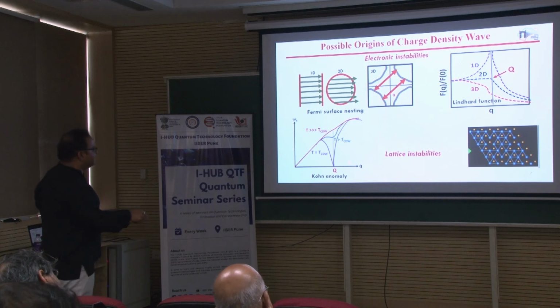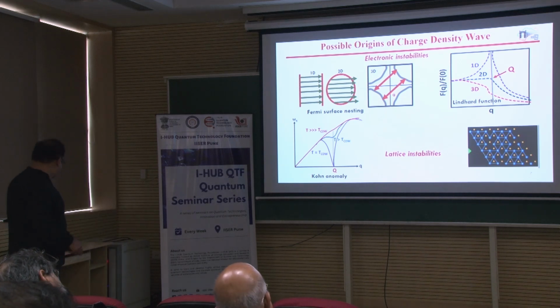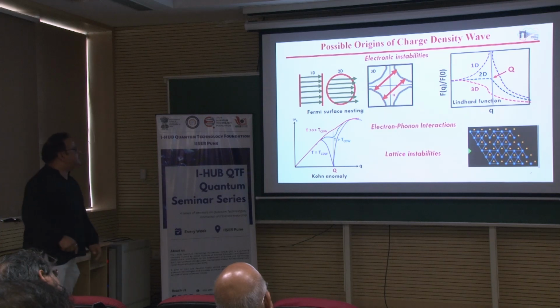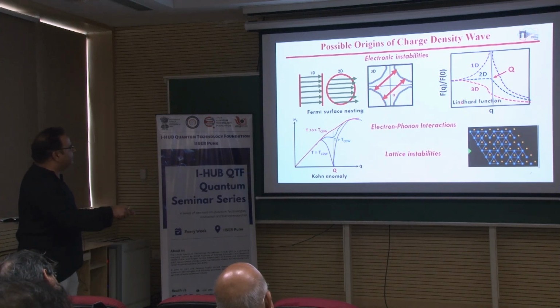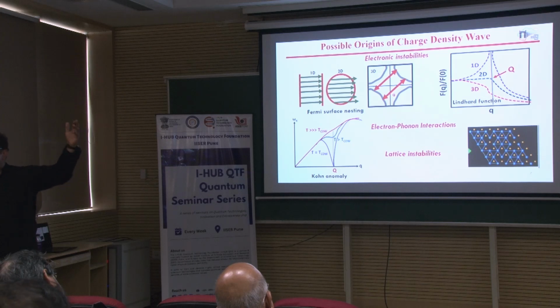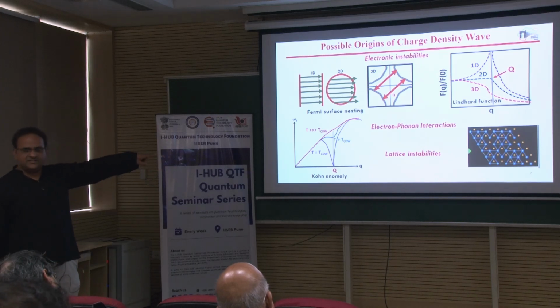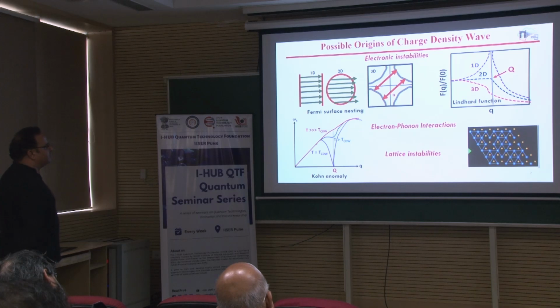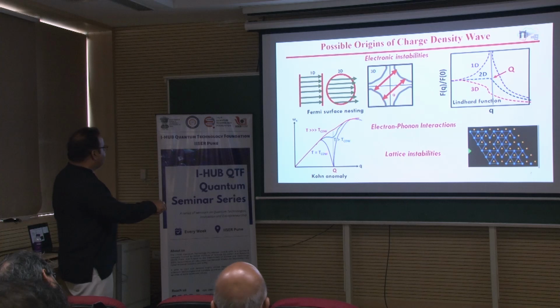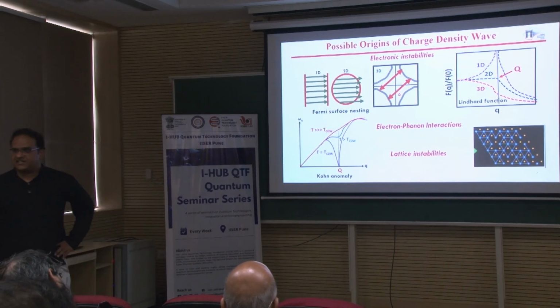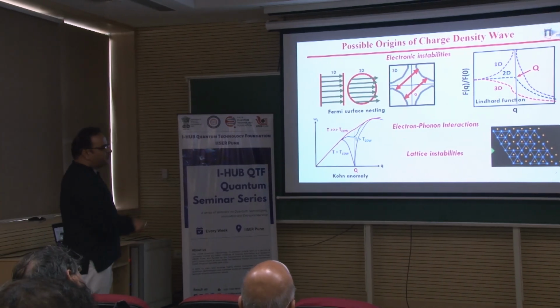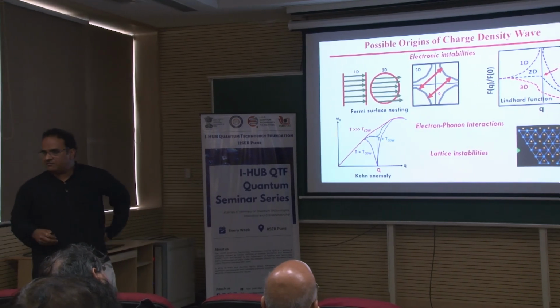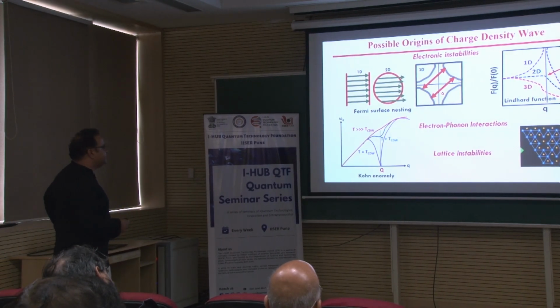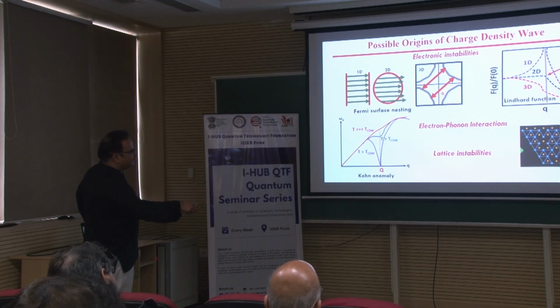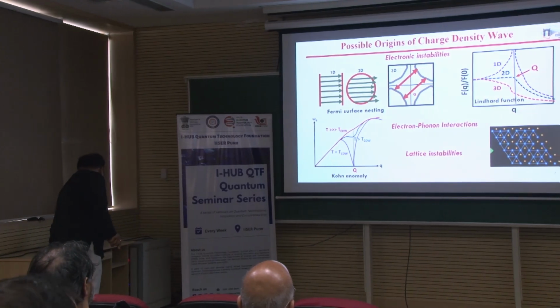So, you have the lattice instabilities which are coming up. And now, how do you compensate these instabilities? You have the electron-phonon interactions, where the electronic instabilities drive the phonon instabilities, and you have the involvement of the electron-phonon coupling. So you have Fermi surface nesting as one of the origins, you have the lattice instabilities which describe the charge density wave, and you have electron-phonon interactions which can be the reason for the charge density wave as well. So, these are one of the ways you can represent the lattice instabilities.